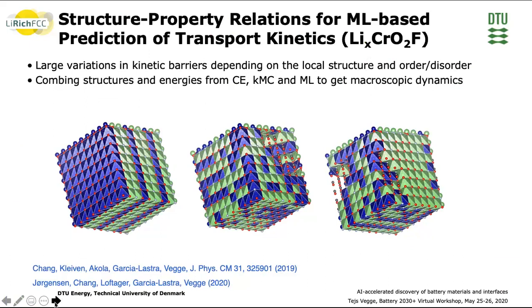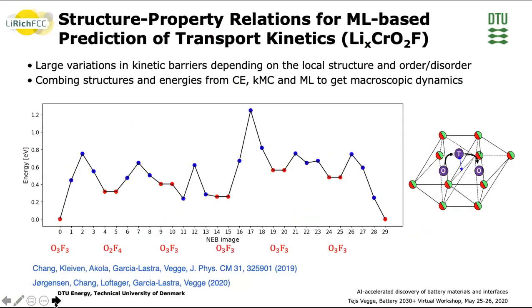And one way that Peter Jørgensen and Jinjun Chang have been using this is to try to establish how the local atomic configuration around a lithium atom moving inside the material controls the barriers. So what you see here is a plot that illustrates a macroscopic transport process through the material. And what you see here is there are a couple of red points that represent local energy minima, but you also see the barriers vary dramatically depending on the local configuration of atoms and the mechanism at play.